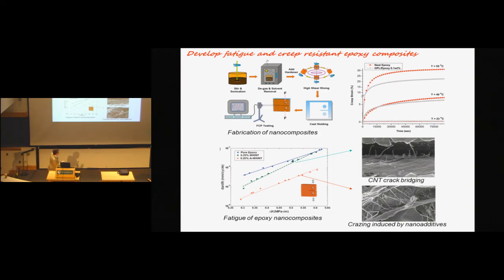Now, when you use the other type of carbon nanotubes, the tubes which have been functionalized with amine, the behavior changes completely. This picture shows again the lower crack face, the upper crack face, but in between, you don't see carbon nanotubes. You actually see fibrils of epoxy. Now, these fibrils will deform a lot. They will deform by like 400%, okay? So extremely ductile. Their dimensions are on the order of 5 to 10 microns, all right? Epoxy does not do that on the macroscopic scale. If you take a big chunk of epoxy and you try to break it, it's going to be brittle, okay? On the small scales, however, it produces this phenomenon which in other polymers, in thermoplastics, is called crazing, okay? So the presence of these inclusions actually changes the nature of failure and the physics of the deformation of this material.